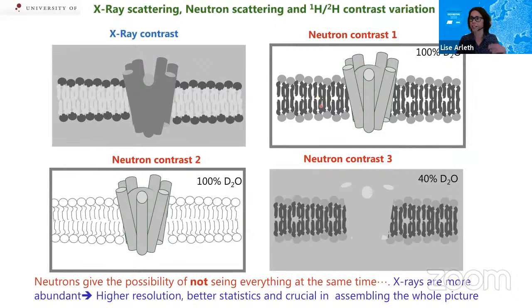So if we don't do anything, but just take our protein and our membrane in 100% D2O, then it'll look more or less like this. We'll have a strong scattering contrast from the hydrophobic parts of the lipid tails and a less strong one from the membrane protein. But then we can deuterate, and I'll talk a little about that later as well. We can deuterate the phospholipid bilayer to make it transparent or invisible to the neutrons. So we can make this match-out deuteration. And this means that we will only be able to see the membrane protein. And this is, of course, very interesting if you want to investigate the membrane protein structure. You could also be interested in looking more at the membrane and how it is deformed in the presence of the membrane proteins.